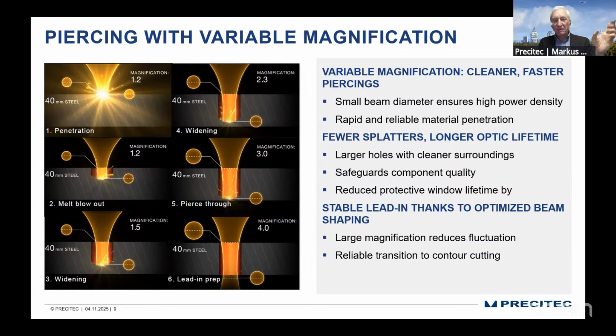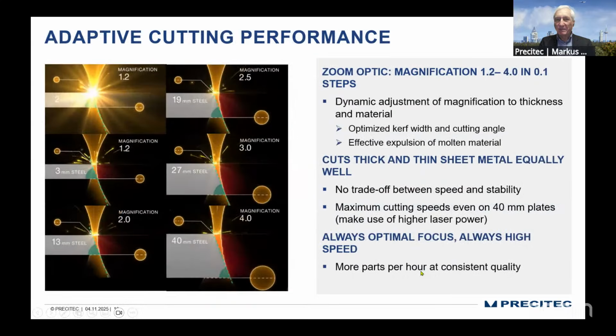And you see that we gradually increase the magnification, which is important to have a very fast and very robust piercing process, because you lose a lot of time if the piercing process is not as fast as possible. So large magnification reduces the fluctuations, and it's reliable. The same, and this is also important, when we start the cutting.